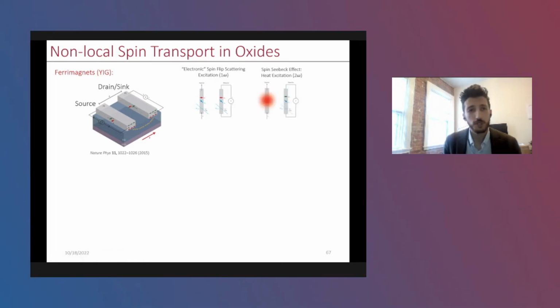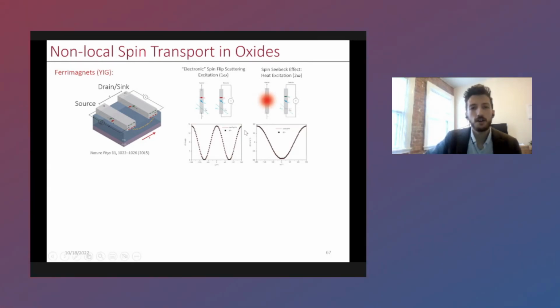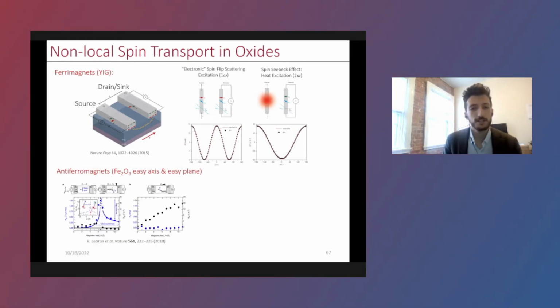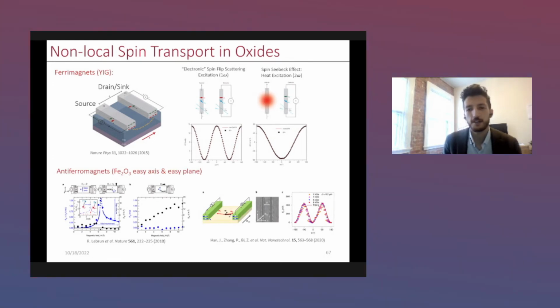But you can also just use Joule heating, the spin Seebeck effect, to create a thermal gradient and thus create magnon propagation as well. And inevitably, both of these happen at the same time, but luckily there are ways that we can actually disentangle the effects of both the electronic and the heat-induced mechanisms. So not only has this been seen in ferromagnets, but also antiferromagnets as well. The common material is hematite, or Fe2O3, and this has been observed both in its easy axis and its easy plane magnetic configurations. What I'll highlight here is that the main mechanisms of manipulating spin waves from one electrode to the other have mainly been using applied magnetic fields.